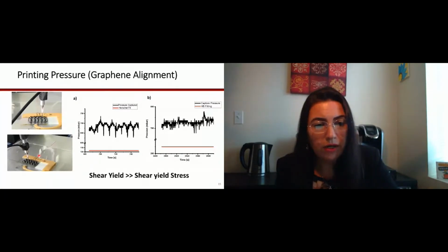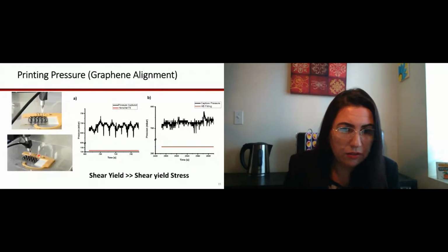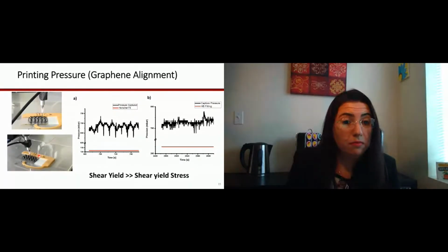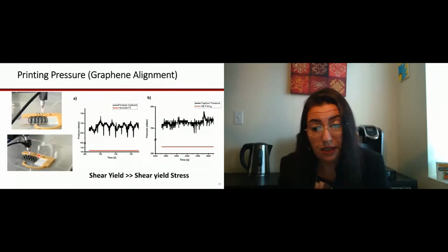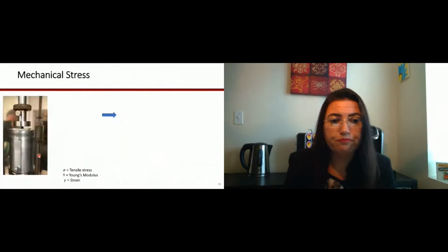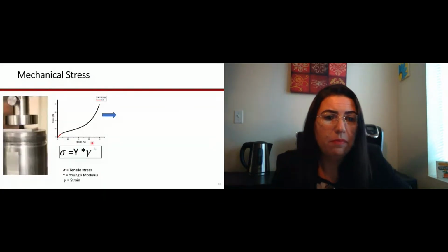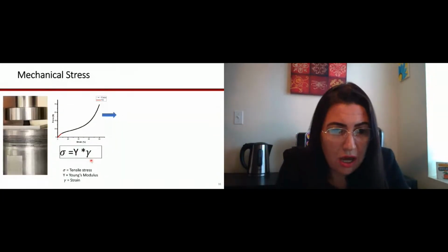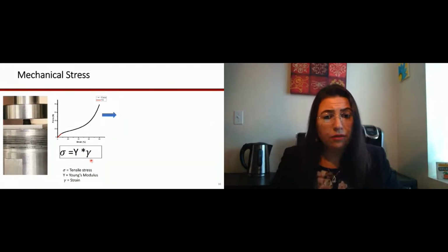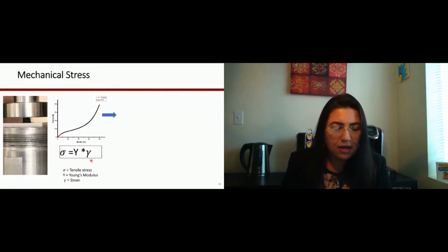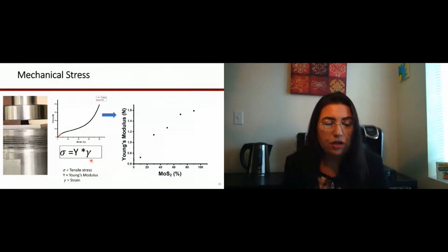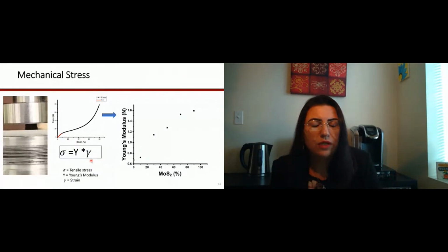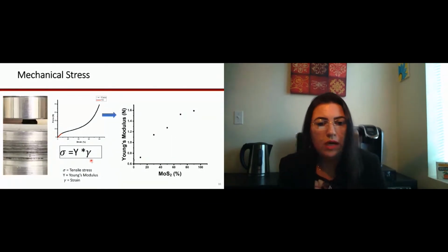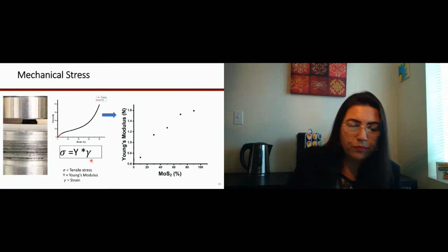So this one that is showing here, the hollow cylinder printed, was for the mechanical stress. That was the first study that I did while I was still in France. So here, what is happening is we're just applying pressure and measuring the tensile stress, and with that we vary the different concentrations of MoS2. And what was really interesting, as you can see, is that as we increase the amount of MoS2, we also increase the stiffness, meaning that the material becomes brittle.